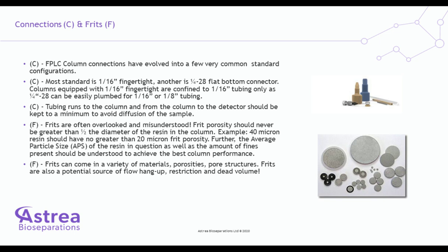So we oftentimes walk a very fine line between looking at our frits and deciding, well, we want the maximum possible frit porosity because we don't want to restrict the flow through our column by having too tight of frit porosity. But on the other hand, a lot of the resins come with a pretty broad range of particle size. So for instance, a 40 micron particle can be purchased from a supplier. And when we look at it, it's 40 micron average particle size, but the range of particle size could be 30 to 60.